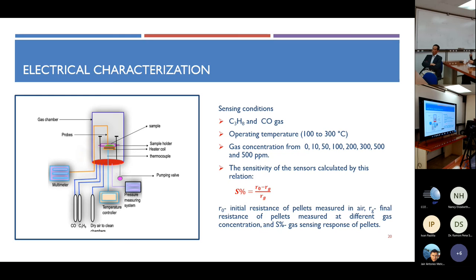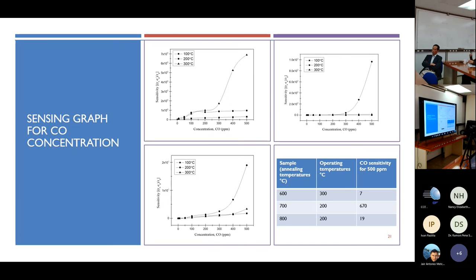I used an operating temperature of 100 to 300 degrees Celsius and gas concentrations from 0 to 500 ppm. For the sensing measurement I used this formula, where R0 represents the resistance in air and RG represents the resistance in the gas. So this is the sensing graph for CO.